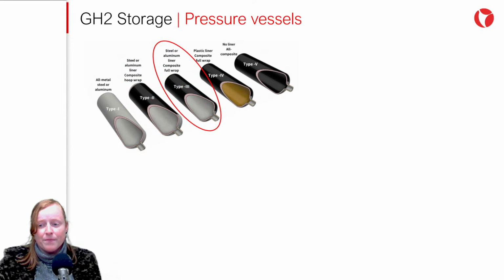Next, Type 3. These cylinders are made up of a thin metal layer called a liner, covered by composite materials. The composite materials withstand the mechanical stresses, while the liner prevents the passage of hydrogen. They have a capacity up to 4 times that of standard Type 1 tanks. This means that smaller, lighter cylinders can be used to store the same amount of hydrogen. They usually have a maximum pressure of 700 bar.